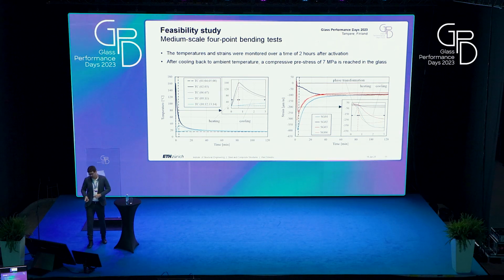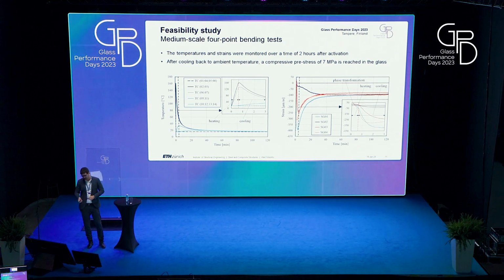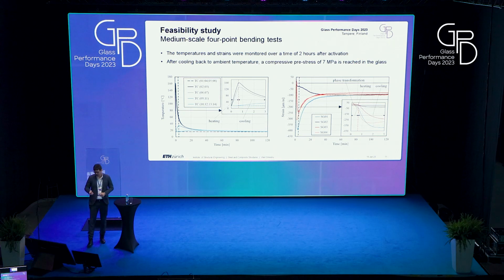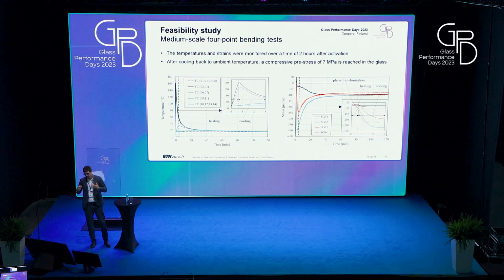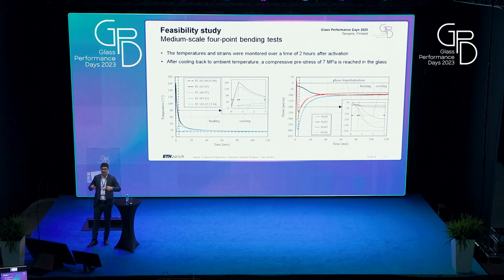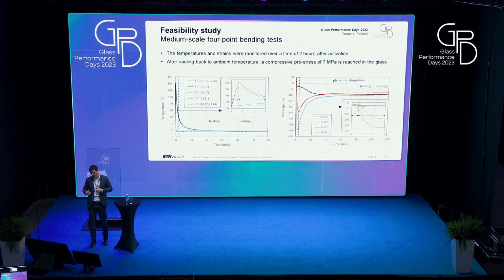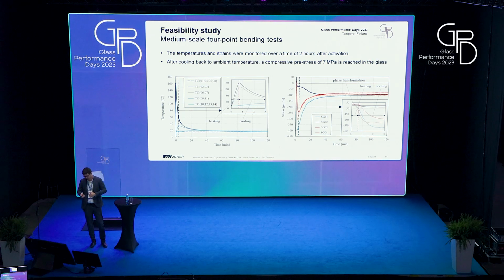I'm just showing you a small detail about the activation. If we look at the first 3 minutes, on the right diagram, the glass first expands when you heat it, like it's normal for almost every material. However, at around 50 degrees, the phase transformation is triggered in the shape memory alloy, and starting with that point, the glass starts to compress.